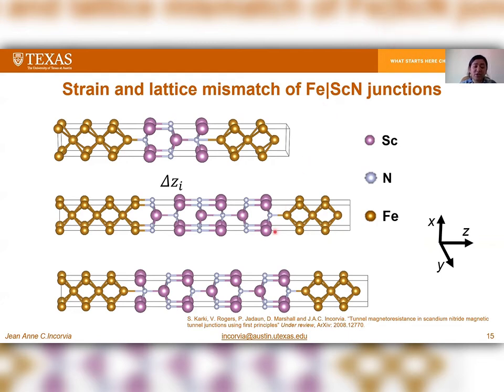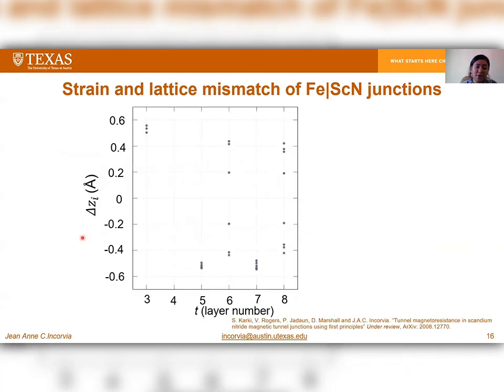The higher lattice mismatch causes dislocation at the interface and breaks the crystallinity. So we looked at the displacement in Z for our atoms from the barrier region, and we see that for the even-layer systems, it is uniformly displaced in the negative and positive direction, and it lets the lattice relax more, which is expected in experiments too. Therefore, it could probably describe why we see higher MR ratios in the 6- and 8-layer systems compared to our odd systems.